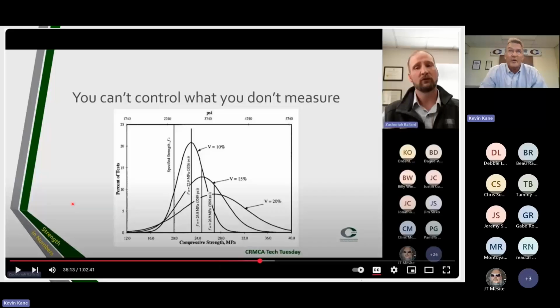So low variability, you're going to make money. High variability, it's going to be tougher to make money. If we look on the left side of the scale here, here's our required 3,000 PSI. If you have low variability, you only need to average, in this example, 3,326 PSI. If you have high variability, if you don't have good control of your materials and your processes, you have to average a much higher compressive strength to satisfy this 3,000 PSI mix requirement.